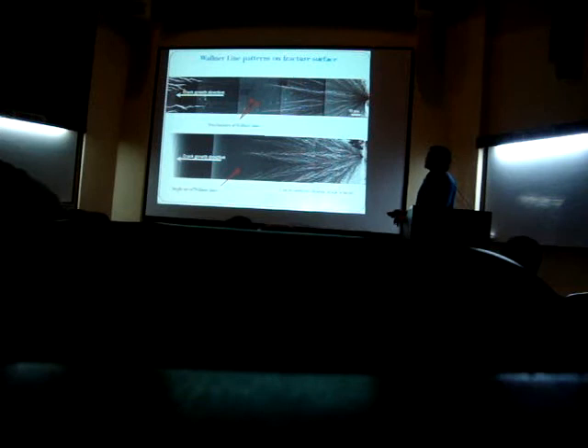I mean, it varies from 79 to 71, but it remains approximately equal to 77 nanometer. And the average height of these corrugations, of these trenches, is around 10 nanometer. What can we do with this?